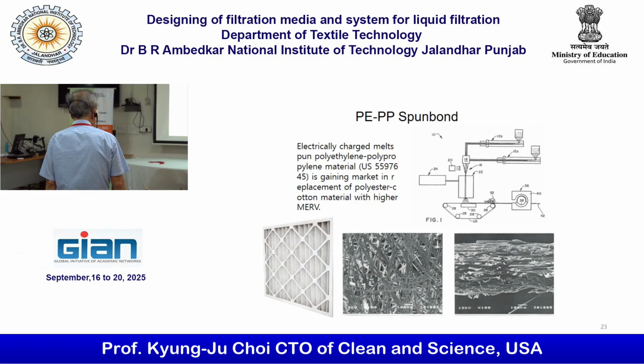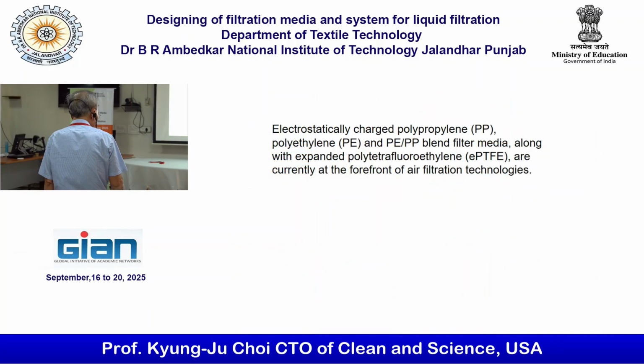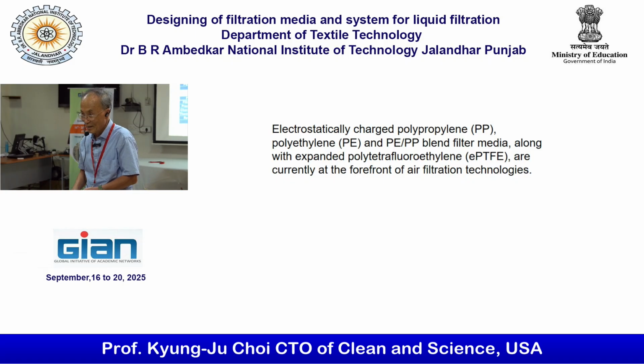Well, this is the air filter, but all of them are made out of polypropylene. So electrostatically charged, expanded polytetrafluoroethylene (ePTFE) is currently used for front of air filtration as well as liquid. Here: charged PP, charged PE, brand, EPTFE, the efficiency, delta P, fiber size, melting point. Look at this, melting point. EPTFE, 327 degrees. Actually, it can go up to 300 operating temperature as well, because the PTFE has a really sharp melting point. That's why for operating temperature, you can go up to 300. And the next one is the charged PP and charged PE, brand, and EPTFE.